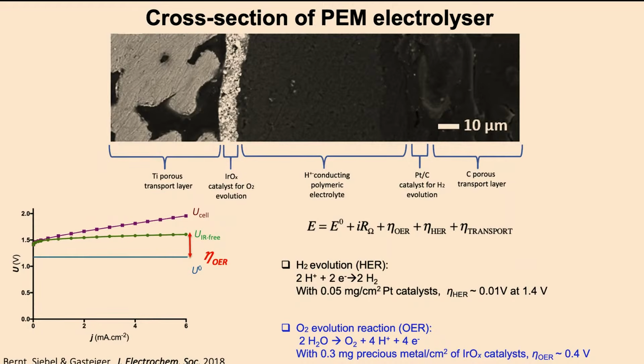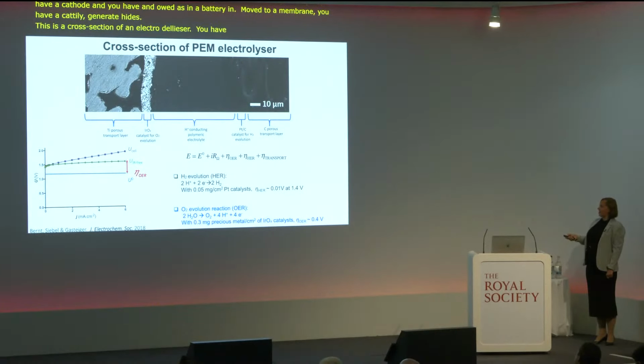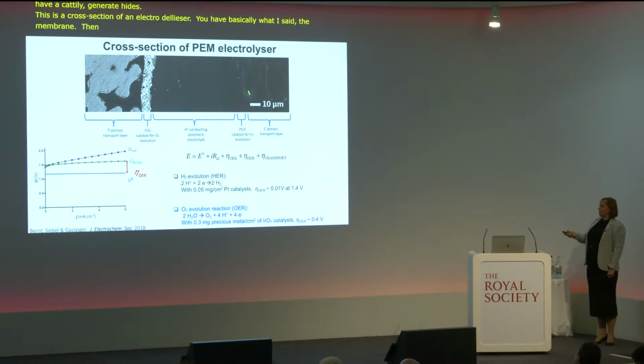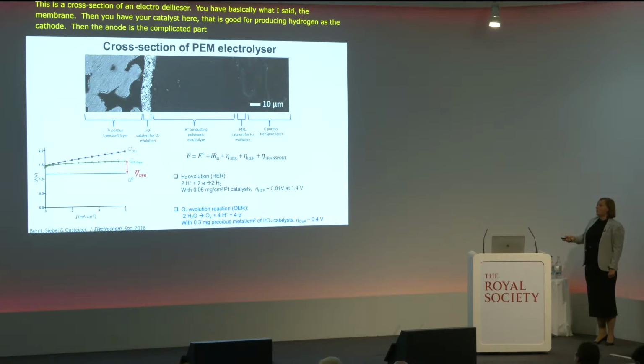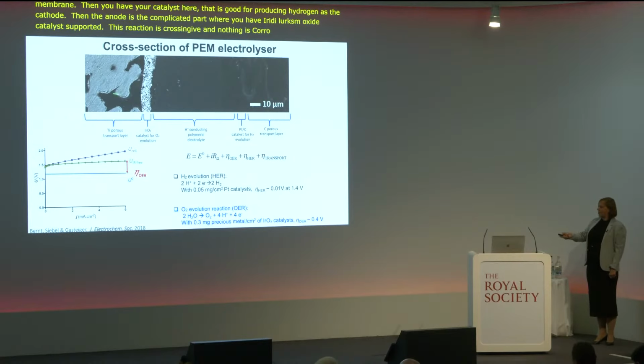This is a cross-section of an electrolyzer. So basically, you have here what I said, the membrane, and then you have your catalyst here that is good for producing hydrogen as the cathode, and then the anode is the complicated part, where you have an iridium oxide catalyst supported on a porous titanium, because this reaction is very corrosive and nothing is really stable. Now, the thing we should be worrying about is this oxygen evolution reaction happening here, so water oxidation.